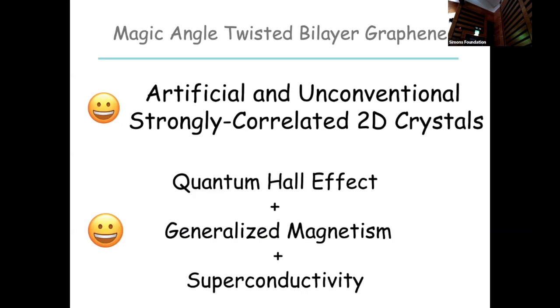And yeah, so I'm certainly not dogmatic about any of this at this stage. I mentioned the optical phonons. The optical phonons, you know, the phonon energy is many times the bandwidth. So those interactions have to be considered as instantaneous attractive interactions, which have to be paired with the instantaneous repulsive Coulomb interactions. And in the slides I went through very rapidly, we look carefully at whether that leaves any channel in which you could get superconductivity due to these instantaneous interactions. And the answer is, it's a little hard to be sure.